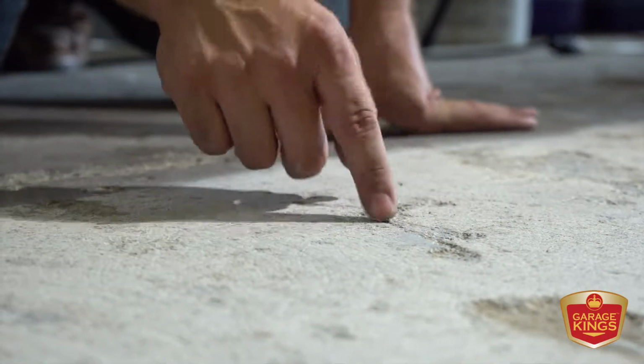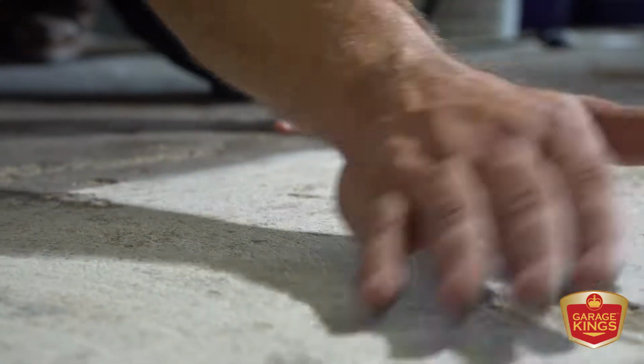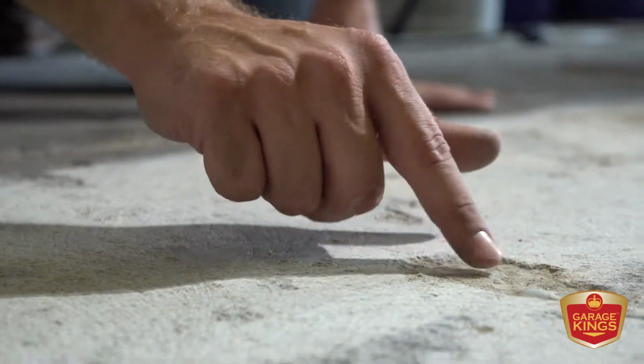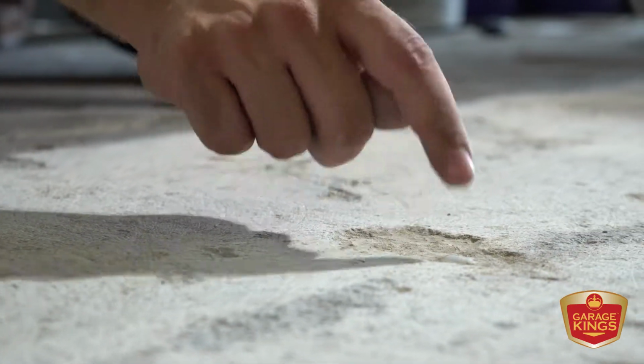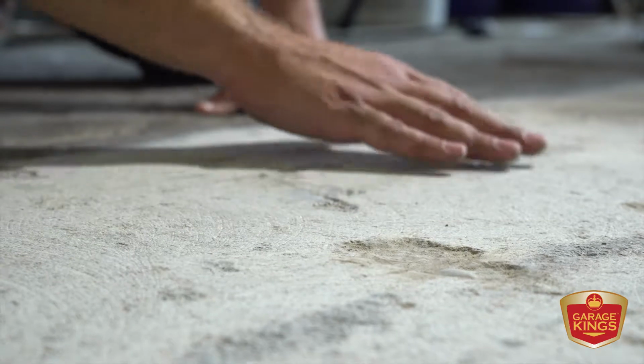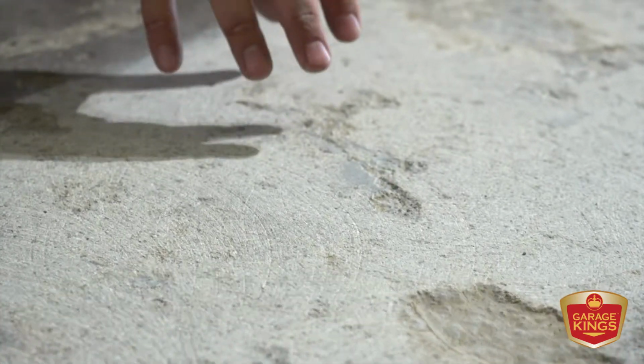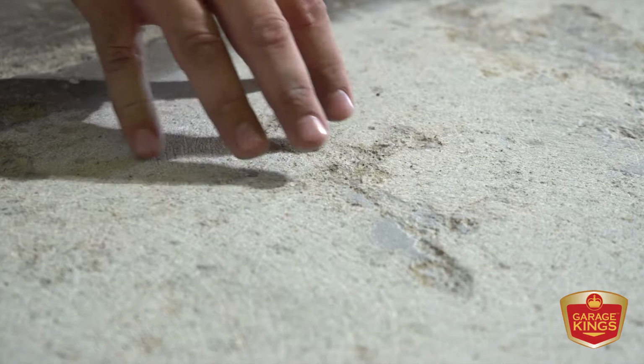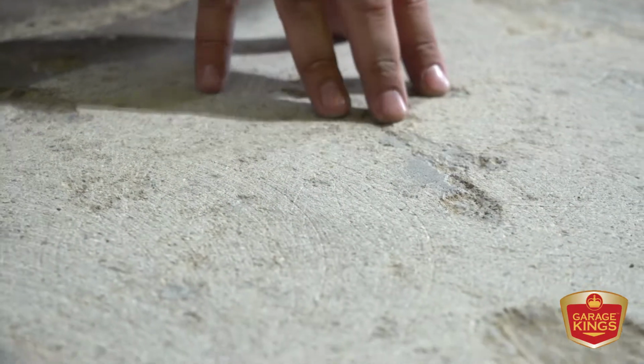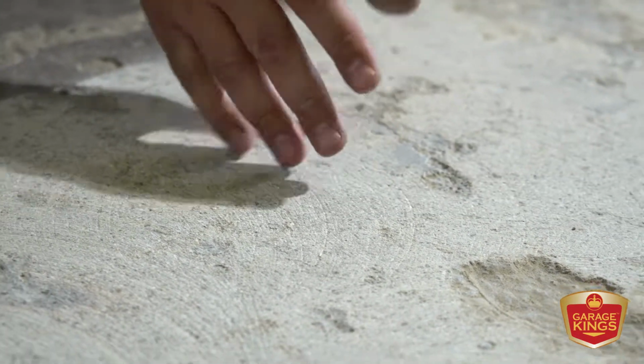But if we have a floor that's heavily damaged or pitted like this one, the diamonds will ride over these low spots. So you can see the dirt still sits in the bottom, and nothing has prepared these low spots for a fill material or even a good coating. So when we run into floors that are heavily damaged or very pitted like this, we're going to take an additional step to our diamond grinding, and we're going to introduce another mechanical prep method called shot blasting.